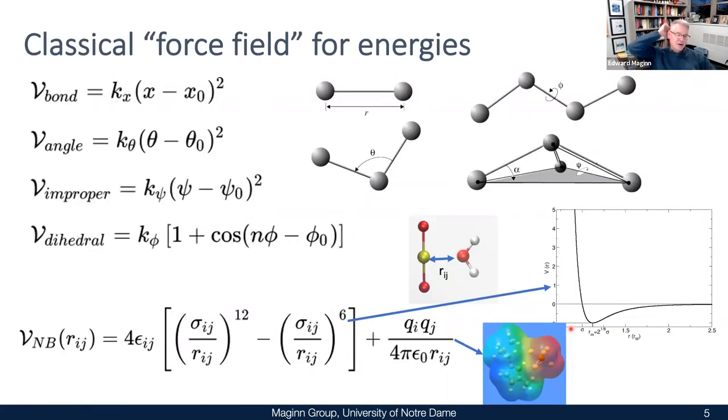And there are many ways that you can represent these energies of materials classically. Here's kind of the standard way that people do. Instead of solving the Schrodinger equation, they parameterize things like the bond stretching frequencies to a harmonic potential. The same is true for, say, bond angles. You can think about a cosine series to represent the energy distribution for rotation about central atoms. Maybe you represent intermolecular distance energies with a repulsion dispersion function that looks like a Lennard-Jones type potential.